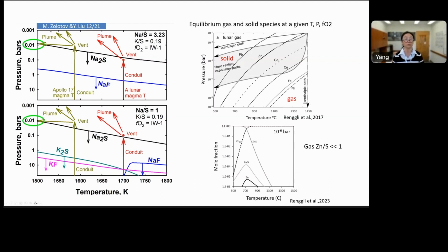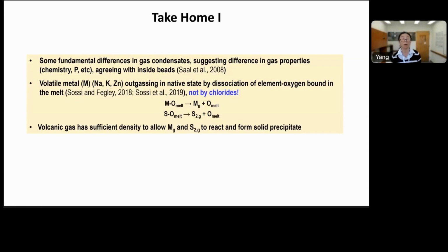Mikhail and I are also performing gas modeling in order to understand the formation of sodium potassium sulfide. This is ongoing work, and we can generate sodium sulfide, but the gas chemistry is key here. So, take-home one for this work: we see some fundamental differences in gas condensates among different volcanic beads. This suggests the volcanic gas can be very different among different eruptions. This also agrees with what was reported for volatiles inside the volcanic beads. Orange and green beads have very different volatile concentrations.